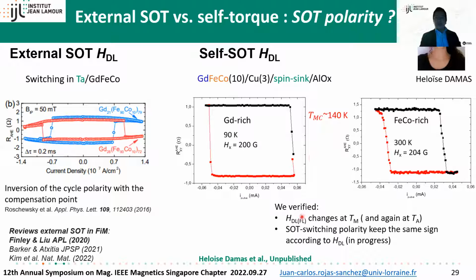And because in the case of the self torque the damping-like component doesn't change, we expect, or we anticipate, that the polarity of the switching doesn't change. And that is what it seems that we observe. We have to double check our experimental results, but we can see that at 90 Kelvin and 300 Kelvin, the switching keeps the same polarity, as we anticipate. So that's what I wanted to tell you.